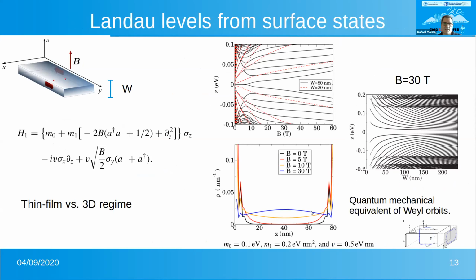Now, instead of solving the states in the bulk, we will solve the states in a slab configuration in this last direction, with the magnetic field perpendicular to the line of nodes. Of course, we can substitute k_z by an operator, and we will have a finite dimension in the z case. Plotting the results of this numerical calculation as a function of the magnetic field for two different widths, we find that the surface states, which in this case live in these two surfaces, depend on the magnetic field. For the longest widths, they are zero modes up to some particular value of the magnetic field where they start to separate. This will be the states coming from the surface, and this will be the states coming from the bulk.